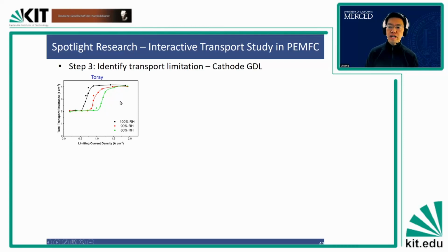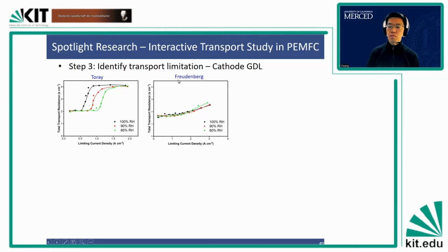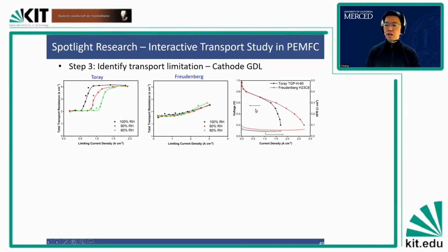And so if you take a look at this on the Freudenberg, which actually doesn't show a drastic transition or a dramatic increase compared to the one on the left. So we observe this fundamental difference. We develop the tool, characterize this material, and then find out that these actually have very different behavior, which is responsible for the difference in performance.